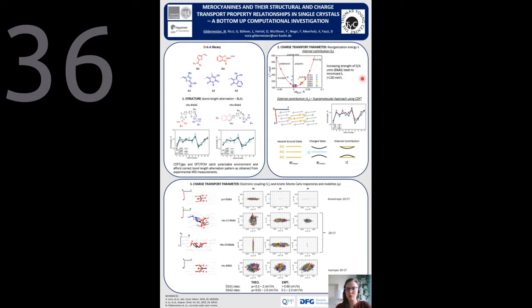Then further, using again constrained DFT and a supramolecular approach, I also calculate explicitly the outer reorganization energy for the merocyanines. And then lastly, I related different solid state packing motifs, as you can see here, with the coupling integrals, and then also the charge mobility calculations and the kinetic Monte Carlo trajectories you can see here. And I could relate the different solid state packing to different directionality of the charge mobilities.